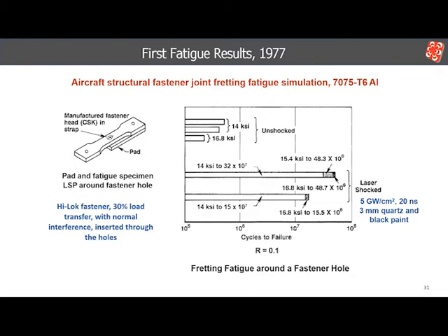During the test, fretting fatigue cracks formed on the fretted surface, but did not propagate into either the pad or the fatigue specimen. This suggested there must be compressive residual stresses in the laser shocked surface. The result became our first and primary demonstration for taking laser shock processing seriously as a metals property improvement tool.